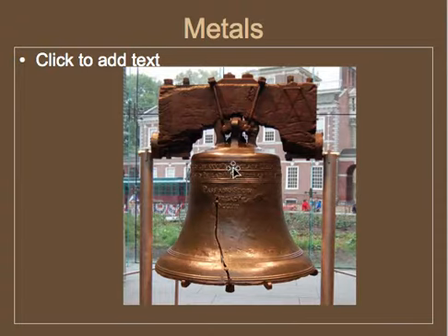Well, it's not homogeneous. So what they think is that when it was recast in Philadelphia, they didn't have a crucible big enough to hold all the metal for one single casting, that they actually had to mix it up in batches and keep pouring using different batches. And because there were different batches, it was not consistent chemically, and that's why you have a difference. Whereas if it was all cast in one session where they had a huge crucible with all the bronze and then poured it, the whole thing would be homogeneous.